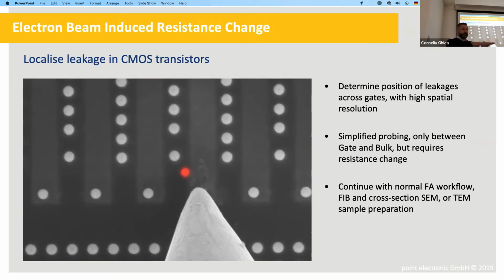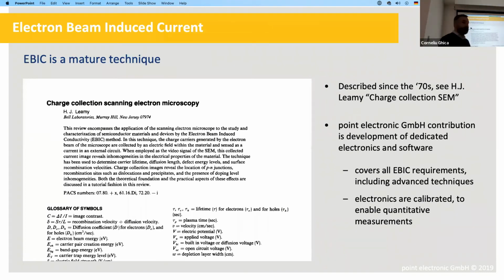Another reason can be local electrical fields. If we have two metal lines very close to each other, as we add a lot of charge because of the electron beam absorbed current, it's possible to change the local transport mechanism, and therefore you can change the resistance and so on. So the origin of contrast can be of very different nature, but the point is that you can localize weaknesses. It's primarily a technique for localization, so where the failure is, and then you would continue with TEM.